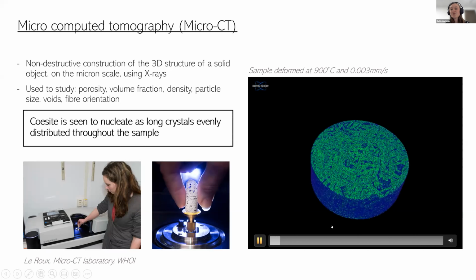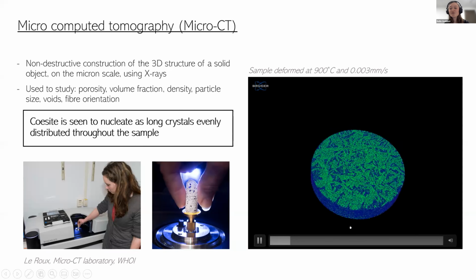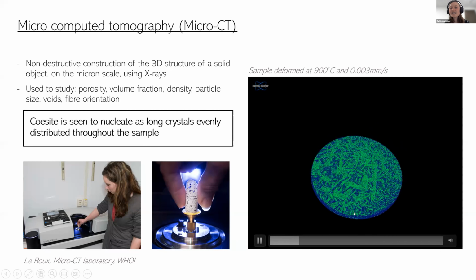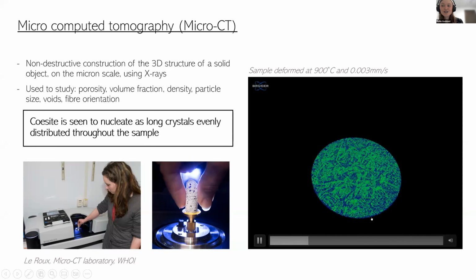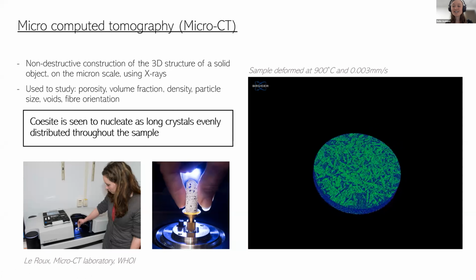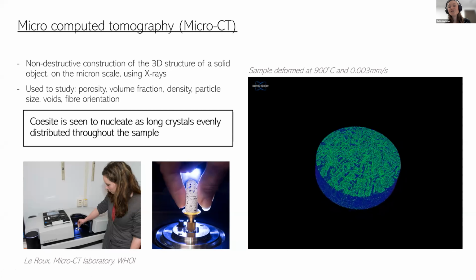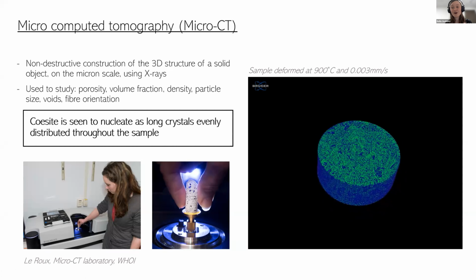So this is one of our samples. You can see in the blue, we've got quartz, and in the kind of green needles, that's the coesite. So we're getting a very homogeneous nucleation of coesite throughout the samples, which means we can pretty much section it wherever.